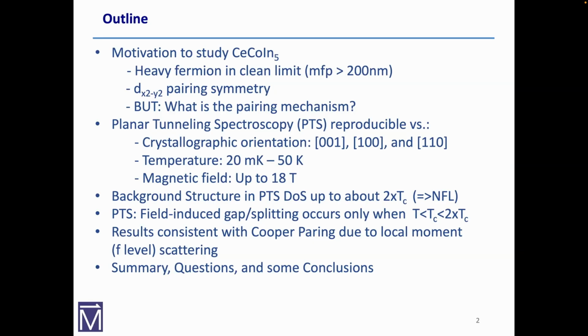So over the past few years we've been able to make very, very reliable planar tunneling spectroscopy measurements. These are all on single crystals that I'm showing you. We do have thin films now, and we're just starting to do tunneling into thin films, which has a lot of advantages. We've been able to get reproducible data in the three major crystallographic orientations: C-axis, A, and AB. We've covered a range of temperatures and fields up to 18T. Thank you, MagLab.